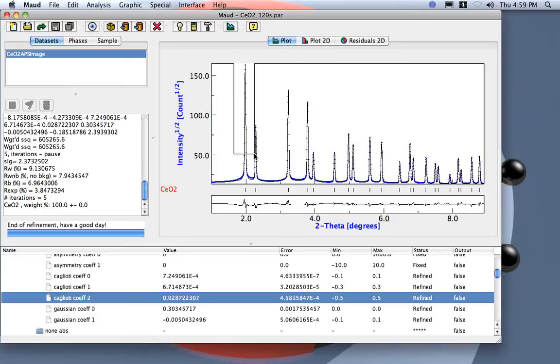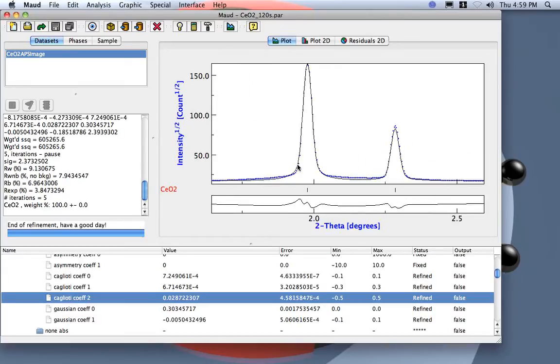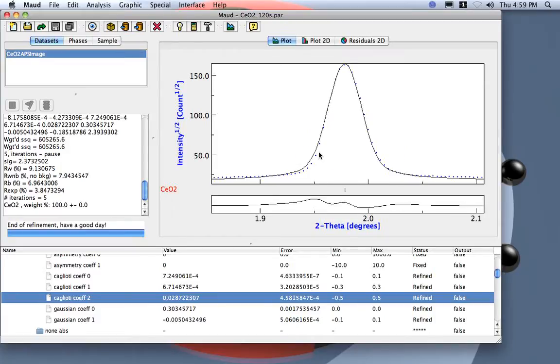The other thing you can see here is there is also a little bit of asymmetry. Normally they are going in the reverse direction with respect to what we are using in Rietveld. This is probably due simply to the geometry where we have a strip detector and the photons are incoming at a certain angle with respect to the detector.